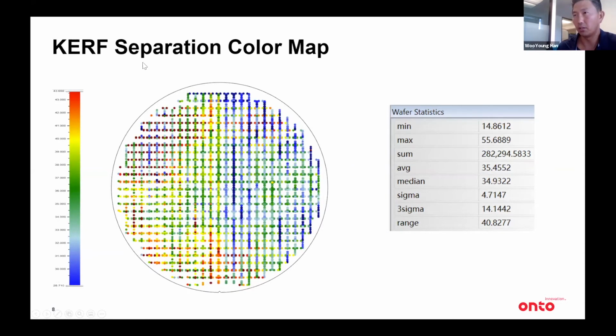And next slide, I have another parameter called the separation. Remember, separation is the actual distance between two dies. So separation will be the sum of materials that has been removed during the sawing process plus the actual amount of stretch on a film, right? So the smaller the separation, the better, right? If you think about it, the less material we remove during the sawing process and the more centered we make the cuts, that will be the ideal sawing process. And that will be the ideal way to avoid all these cracks and chippings from happening.